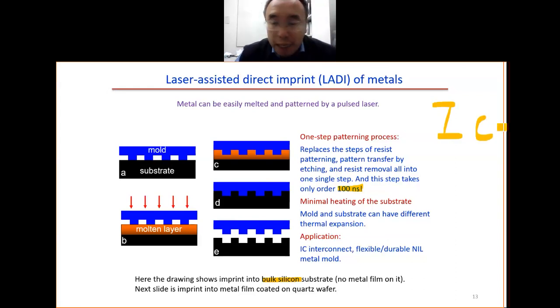But the problem is that later on, people found out that we have this molten silicon that's solidified. It is cooled down very fast. The silicon here, the top layer here, becomes amorphous. It's no longer crystal. It becomes amorphous silicon, or maybe polycrystal silicon. We know amorphous silicon and polycrystal silicon are not very good for the device. They have a lot of defects and very low mobility.